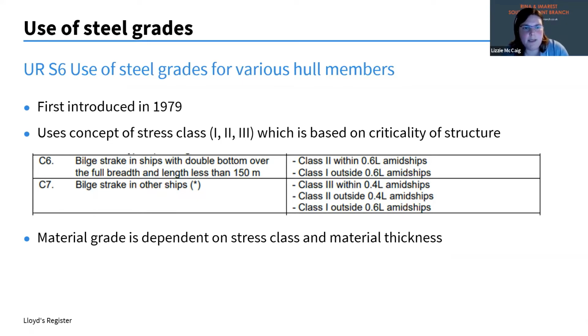So for example, here you have a bilge strake in ships with a double bottom, over full breadth and length less than 150 meters. You can see here that class 2 is within the 0.6 L midships and class 1 is outside. So class 2 is a more onerous requirement than class 1. And then for larger ships and for single bottom ships, we've now got class 3 within the midship region, and then class 2 tapering to class 1.